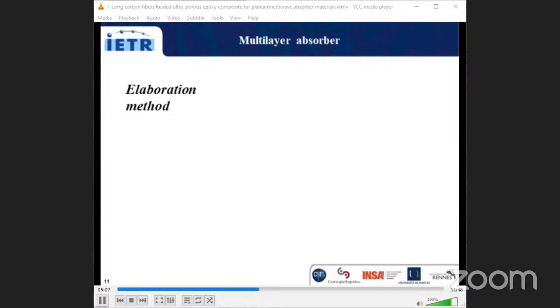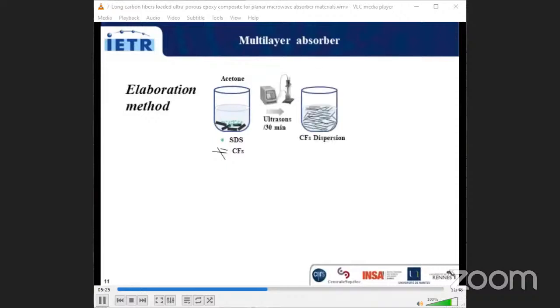I present here the elaboration method of the ultralight epoxy foam. First, we start with the pre-dispersion of carbon fibers of 12 millimeter length. These fibers are added to a solution of acetone and SDS, which is a chemical dispersant, after which ultrasound is applied to disperse these fibers. Then the dispersed fibers are added to the epoxy resin.